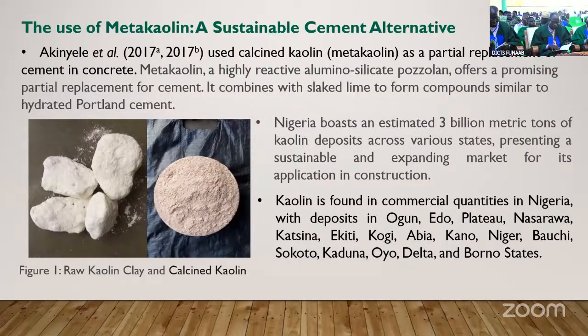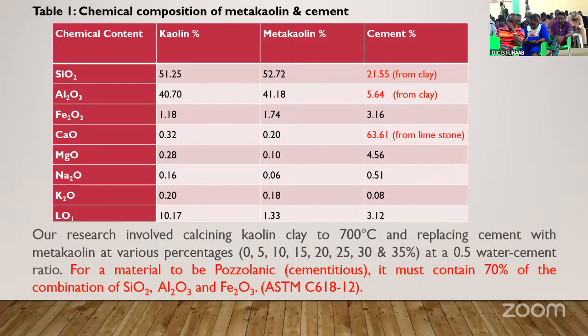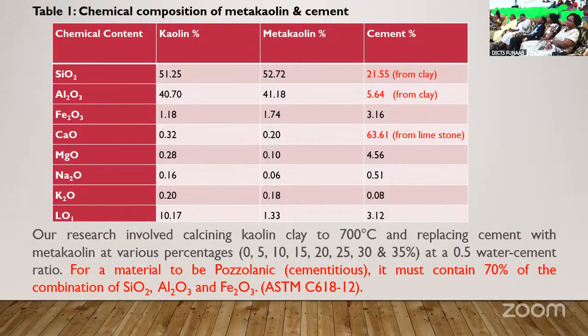Kaolin is found in commercial quantities in Nigeria with deposits in Ogun, Edo, Plateau, Nasarawa, Katsina, Ekiti, Kogi, Abia, Kano, Niger, Bauchi, Sokoto, Kaduna, Oyo, Delta, and Borno states. On the chemical composition of metakaolin, from table 1 above, we can see metakaolin having silicon oxide, aluminium oxide, calcium oxide, and ferrous oxide. These are the main things that we have in our cement that make it cementitious. Our research involved calcining kaolin clay to 700 degrees Celsius and replacing cement with metakaolin at various percentages of 0, 5, 10, 15, 20, 25, 30, and 35% at a 0.5 water cement ratio.